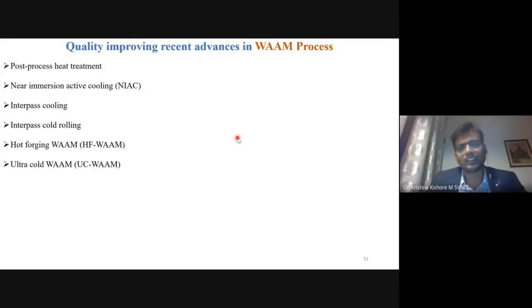Now, if you want to improve quality further, there are two drawbacks that this WAAM process has. If we deposit one layer over the substrate, the substrate absorbs the heat. Let's assume we deposit a second layer on top of the first, and then a third layer. Because of conduction, the heat is absorbed by layer 2, layer 1 and the substrate. As we keep depositing, the layers on top spread the heat towards the bottom. The bottom microstructure is a little coarser grained, with columnar growth, or simply anisotropic property from the bottom to the top. So the property from the bottom to the top of the deposition is quite different.